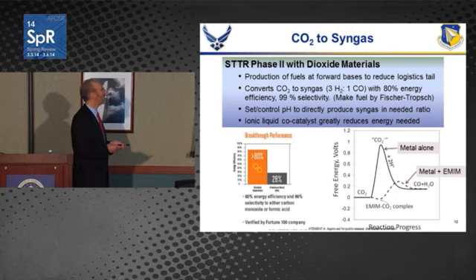It now goes from CO2 to syngas, this 3-to-1 ratio of hydrogen to CO, with about 80% efficiency and very high selectivity. And that syngas can then be turned into gasoline by a Fischer-Tropsch process. And by controlling the pH of this process, they can control the ratio of hydrogen to CO.